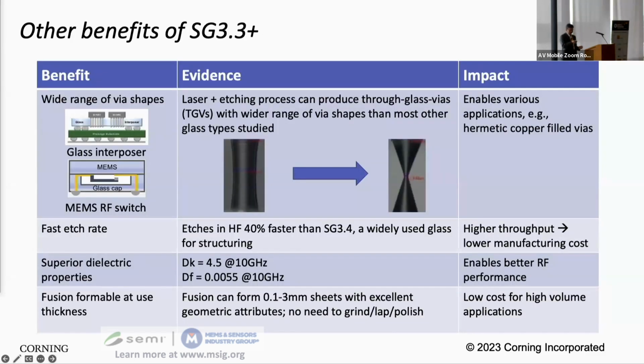And another reason we like this glass is this fusion formable glass that we call SG 3.3 Plus has the unique property of being able to have vias that we can change the shape of. And this is important because, as I said, some applications benefit from through glass via, and the ability to change the shape of the via allows you to metallize such vias with more flexibility. For example, if you wanted a hermetic seal in the metallized via, a necked shape allows you to do that much more so than if it's a straight via. So we like that. And then it's also, in acid etching, much faster than some other glass types, which means if you want to form vias, you can form vias at high throughput and low cost.